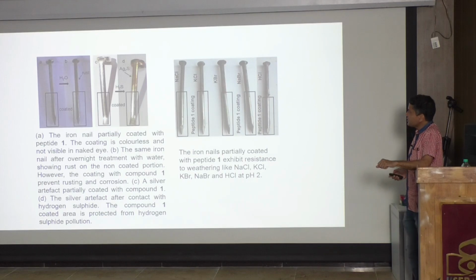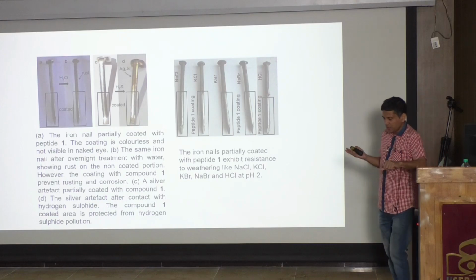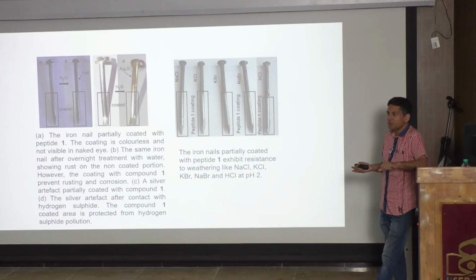Not only that, so this is a silver article. We know that if you use silver ornaments for a few days, and there is hydrogen sulfide in the air, the silver will react with hydrogen sulfide and turn black after a few days. So we covered the silver article again with our material and put it inside the hydrogen sulfide chamber, but nothing happens in the covered area. So you can protect your ornament from silver sulfide formation.